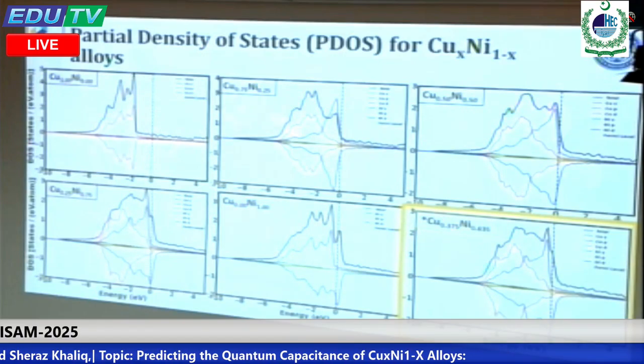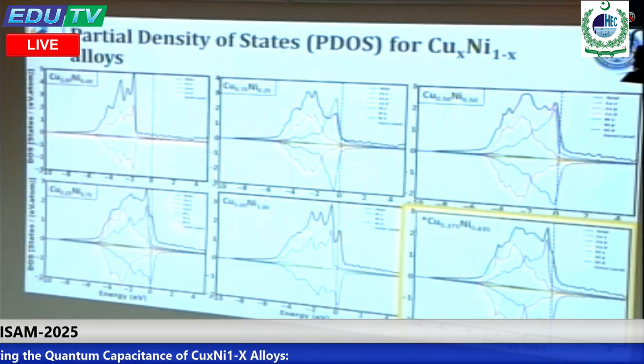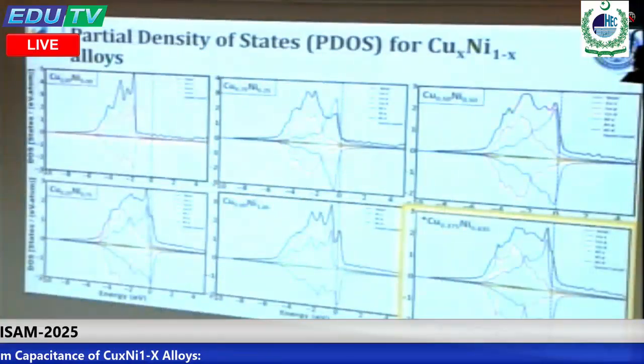But with the inclusion of 25% of nickel, the density of states at the Fermi level is increasing, and after 50% it increases much more, up to 100% of nickel and 0% copper. But we didn't know which composition is best for the density of states. So this is our testing alloy that can be used to test our model.